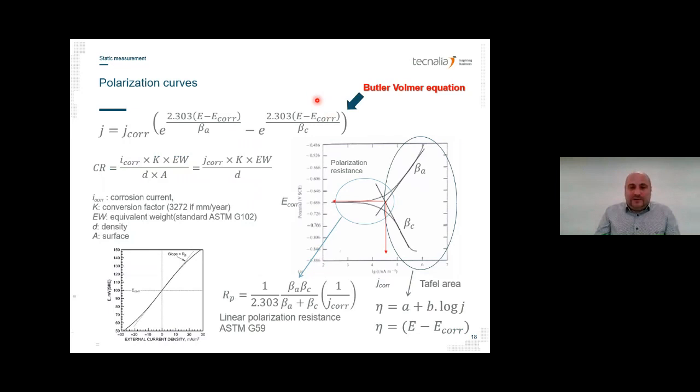And here comes a very important equation for electrochemistry, the Butler-Volmer equation. This one equation links our overtension, which is the difference between this value, Ecorr, and a value that we choose far from Ecorr. It links this value, the overtension, to the current density. That is very important. So we can see that here there are two coefficients. And if we put it in the logarithmic scale and we go to this point, so Ecorr here, we will be able to extract this value that is the current,